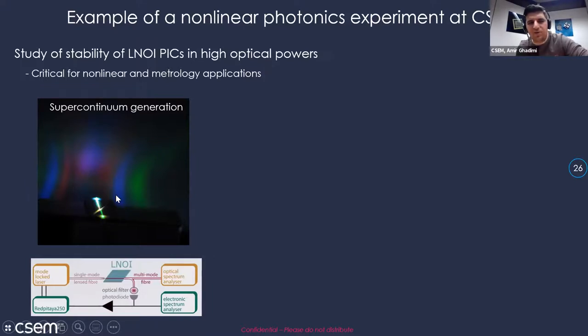So what you see on the left is just a 5mm by 5mm LNOI chip, and it's just a waveguide stretched from one end to another. From the bottom side, we are coupling with a lensed fiber, irradiating this with a mode-locked laser at 100 megahertz repetition rate, average power of 50 milliwatts. As it passes through the waveguide, the nonlinear effect is so efficient that out of 1550, which we are pumping, you can create other colors, so efficient that you can even see the color blue. On the other side, normally we have a fiber, but now we put a piece of paper just to shine on it to take this image.